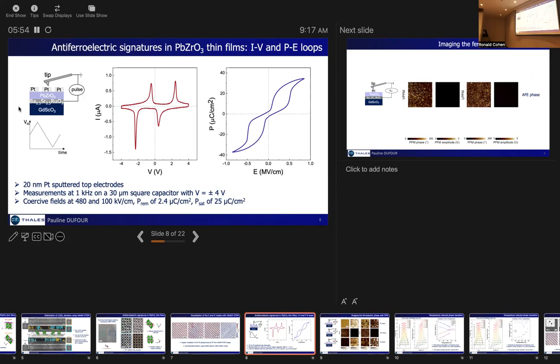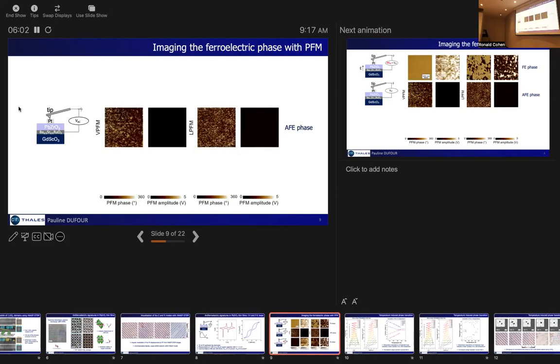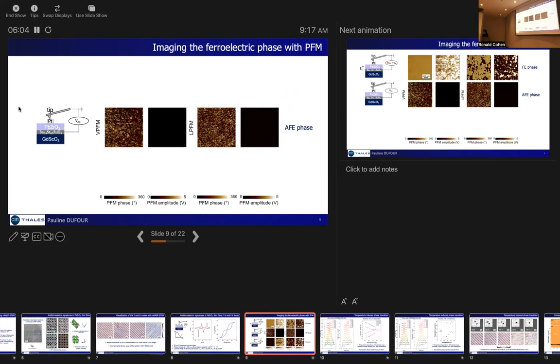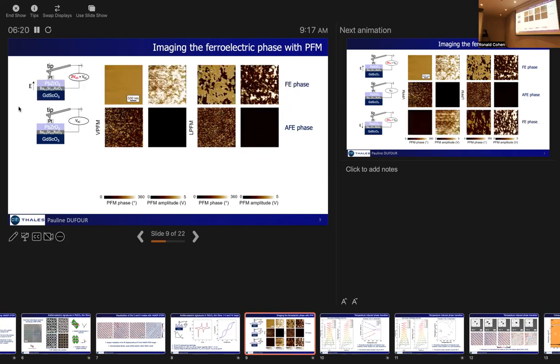Now we wanted to investigate in more detail the electric field-induced polar phase by PFM imaging. So first we probe the antiferroelectric phase by applying a 2-volt peak-to-peak AC, and we observe that in both vertical and lateral PFM, the phase is in the noise background, and this is accompanied by no detection at all of the amplitude. Then we add a continuous DC to probe the ferroelectric state.